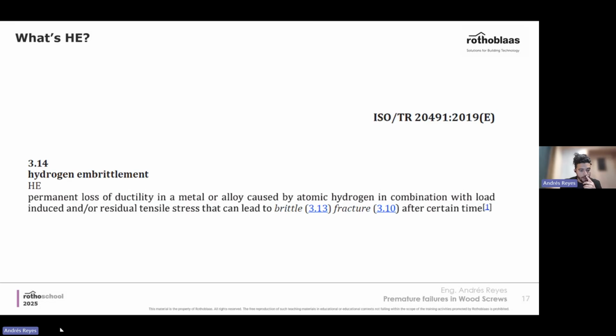So it's the permanent loss of ductility in a metal or alloy caused by atomic hydrogen in combination, always in combination with load, which can be induced or residual tensile stress, that can lead to a brittle failure after some time. So these factors are necessary. We're talking about a loss of ductility in a metal caused by the presence of atomic hydrogen. That means if there's no atomic hydrogen, then there's no hydrogen embrittlement. And that means as well that there's always a load needed.